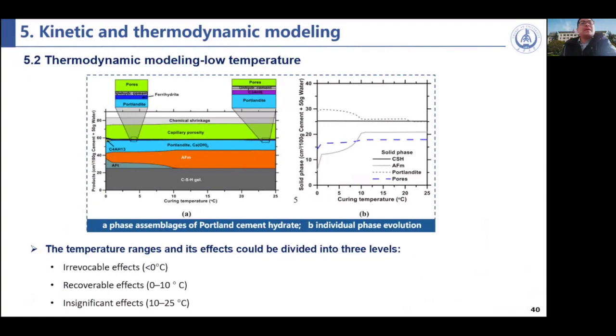thermodynamically changed. So we have to put in more phases at the phase changes during this temperature, and also the durability will be reduced in this temperature. If the temperature is between 10 and 25 degrees, we call it insignificant effects. That means the hydrates are stable, and the hydration is similar to that with the standard conditions. So